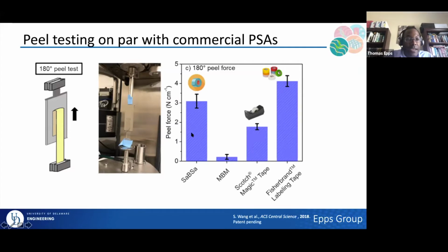Before I move to the data, I do want to focus on one particular thing, which it might be hard to see here, but if you actually see our tape, it's pretty clear. And so the nice part about this material is that liquid-liquid extraction and that catalytic depolymerization allowed us to really get rid of the brown color and again produce a nice, clear, aesthetically pleasing material if I start thinking about tapes and other applications where I don't want a material that's necessarily black or brown.